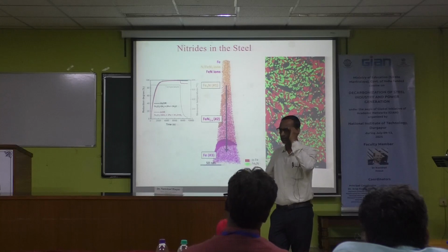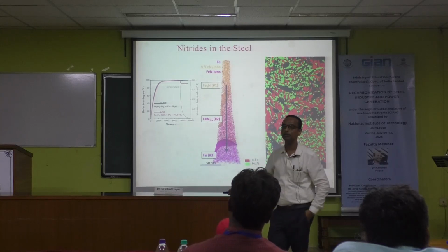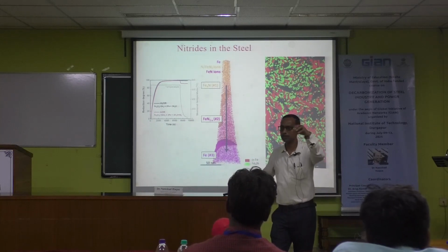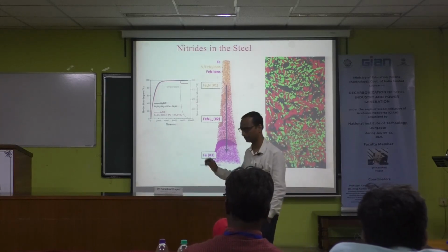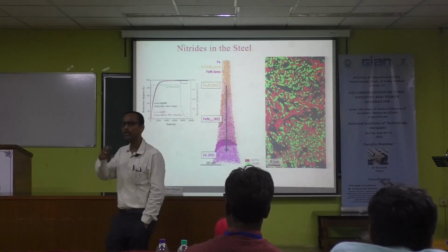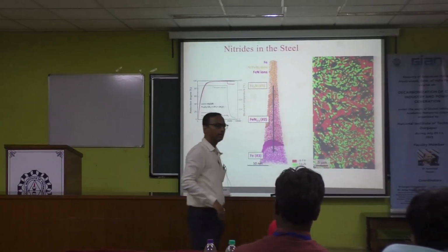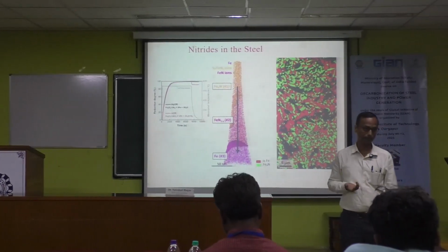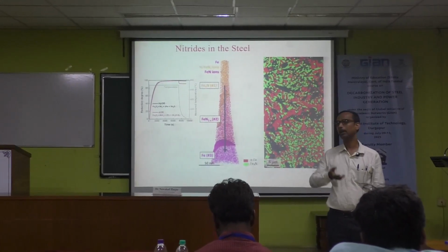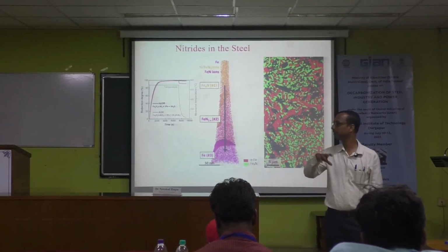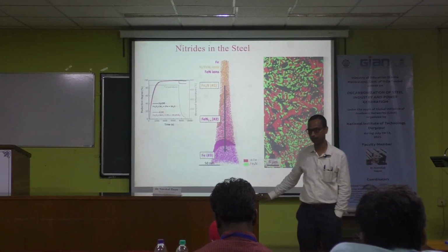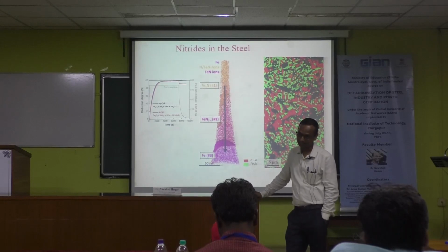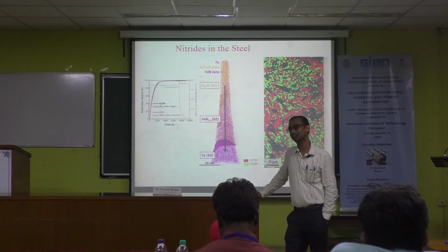They observed the extra dissolved nitrogen; when it goes to the liquid phase, it will come out. It depends upon how much nitrogen is absorbed, on the concentration of the nitrogen. Then it will come out. And for degassing we have facilities now, so from that treatment it can easily take out the dissolved nitrogen. There will be no problem. It will be beneficial for stainless steel.